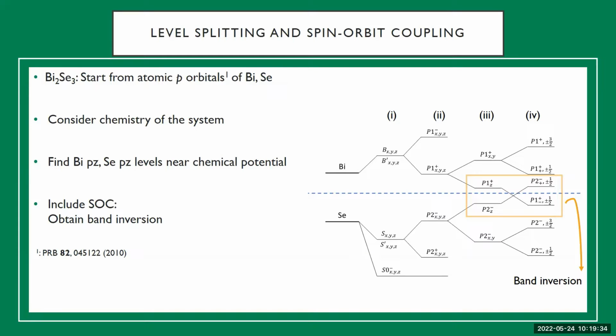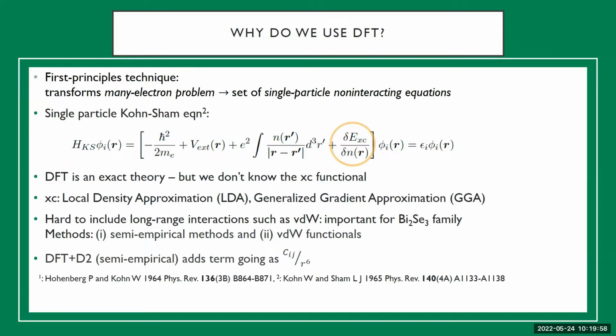And this is what's called band inversion. And that ends up being the reason for the topological nature of these materials. And these two levels, or rather all of these levels on the rightmost panel, play the most important role in giving rise to the low energy properties of the system. So this model, which I talked about previously, relies on various parameters, such as the initial splitting between the bismuth and selenium p orbitals, etc.